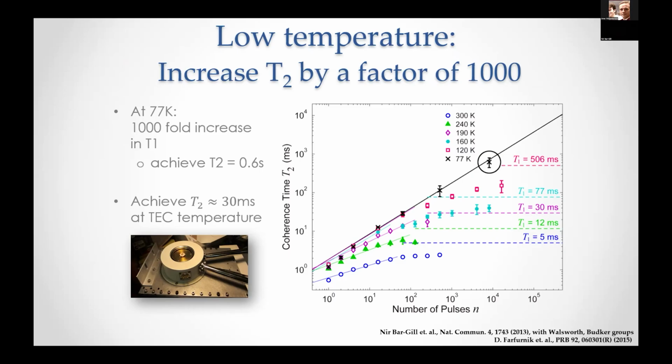But the phononic environment couples within itself extremely quickly. It's something that we sometimes call a Markovian reservoir. It has no memory. And if it has no memory, it means that on each side of the pi pulse, no matter how many pi pulses we have, the noise will be different. So our control can never be fast enough. Our sequence of pi pulses can never be fast enough to decouple or suppress this phononic relaxation.